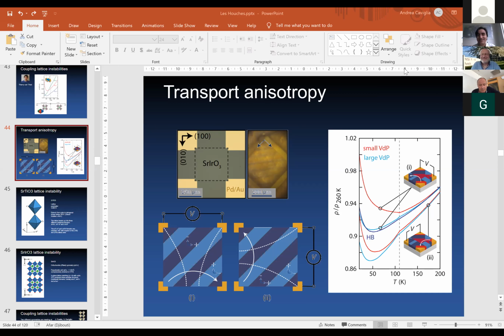I see. So actually, from work we've done with them on the ferroelectric STO with calcium and LAO interface, we also see this tendency for the 45-degree, but I guess it's a different reason there, because we at least speculate it has to do with the ferroelectric polarization. That is another interesting point. There are some indications that there is a polarization along these domain walls, and it may play a role in influencing the conduction properties of these domains. Yeah, but I would leave it as an open point. Okay, thank you.